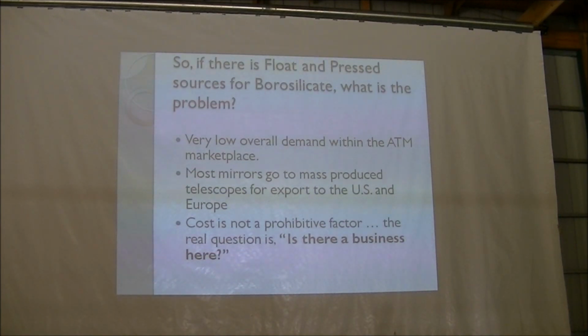And I mean, there's another really great material. I think it's the greatest thing since sliced bread. That's sintered silicon carbide. It's the lightest, strongest, zero expansion material I think you can get your hands on. And it's tough as nails, but it's just expensive as hell. That's what a lot of space-based optics are made out of, because a big blank like this weighs about 3 pounds.